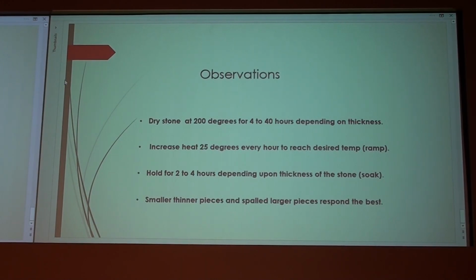Is there any evidence of that? Is there actual evidence that you found digging? They found a bunch of bifaces buried once in sand, like described. And then replication too. And you can see it when you find flakes, you go, that's been heat treated. So you know what you're doing. Are there any dates and stuff like that? Chinese are probably doing it before. Here in the state, here in Kansas, and possibly up here, it's only during the late Archaic that you see it done a lot. Prior to that, not so much. But again, that might depend upon your source material too.